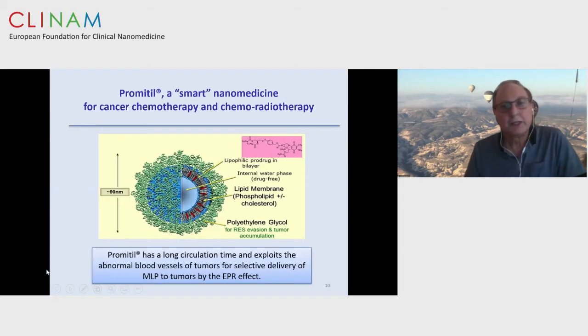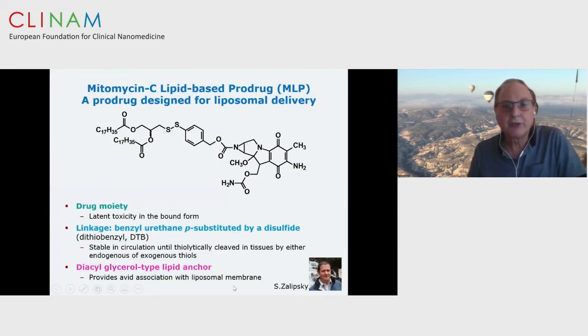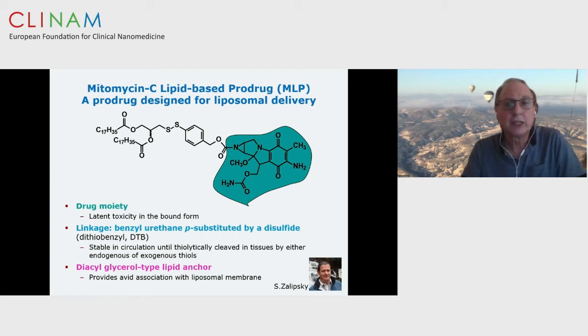But the topic I wanted to dwell on today is about Promitil. And here, from the inspiration given by Doxil, we designed a product in which we have a liposome with the same liposome characteristics. It is a pegylated liposome of the same composition as Doxil, but we actually synthesized a prodrug of mitomycin C, which is extremely lipophilic, and that is tailored to perfection for incorporation in the bilayer of these liposomes. And so we try to exploit again the EPR effect for delivery of this prodrug of mitomycin C to tumors. This product was developed together with Dr. Zalipsky, who was then at ALZA Corporation, and it includes mitomycin C, of course, which is the active moiety.